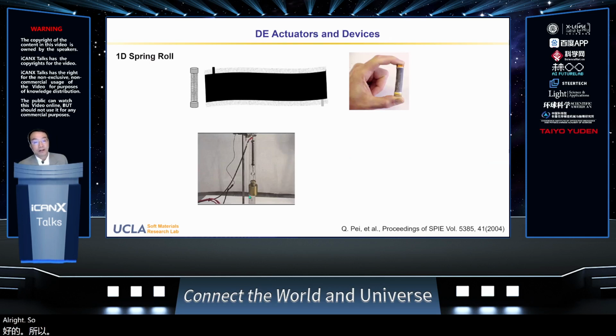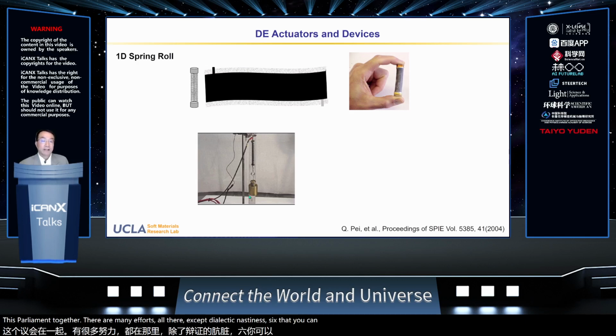All right, so these are soft rubbery films. To deliver high force output or power output, we have to stack this polymer together. There are many efforts out there to stack dielectric elastomers, thick stacks, to generate a high thickness stroke and high force output. One of the approaches we took was to make what we call spring rolls. You first stack 2 dielectric elastomer films with carbon-based electrodes, and then you wrap this 2-layer stack around a central spring.